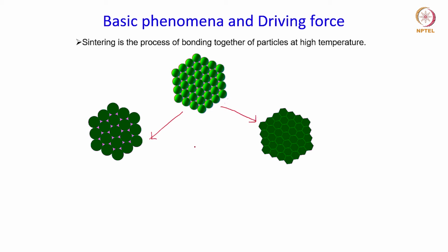Okay. If the pores are located along the grain boundaries during the final stage of the sintering process, then it is expected that they will retard the grain growth, and the grain growth will not be very significant. It will be a normal kind of grain growth. On the other hand, if the pores are located inside the grains, then there is a chance for abnormal grain growth, because now there are no more pores along the boundaries to pin them, and as a result of that, the grains can grow abnormally.